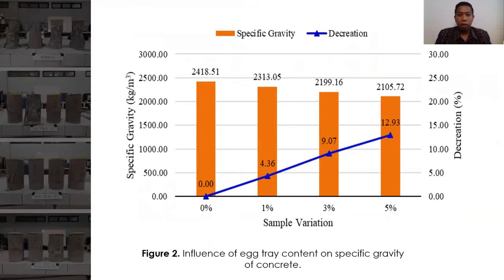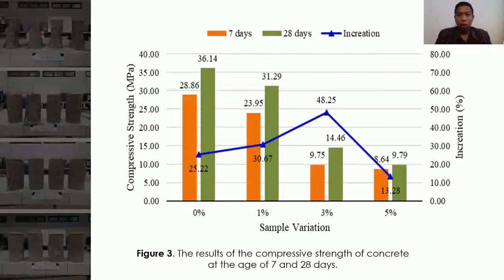This shows that there is a significant decrease in the specific gravity of the concrete with the addition of egg tray to the concrete mixture. For the percentage variation of 1% egg tray, the specific gravity decreased by 4.36%. And with an increase in the percentage variation of 3% and 5% egg tray, the specific gravity of the concrete decreased by 9.07% and 12.93%. Based on the result of testing the compressive strength of concrete for each sample variation shown in figure 3,